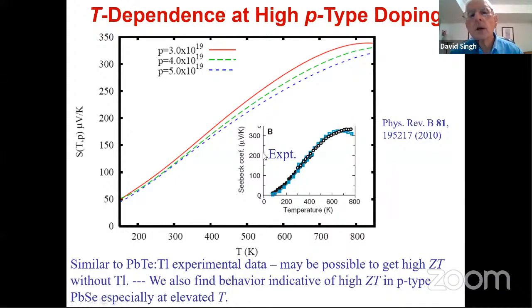And this is some experimental data. And the experimental data agrees very well with the theoretical curve, which you might think is sort of uninteresting. But it is interesting. And the reason it's interesting, this was work from 2010 that I published then. The reason it was interesting is this was not the standard experimental data for lead telluride. This was experimental data for what was called a very special kind of lead telluride, which had thallium in it, which was thought to change the band structure. But the calculation was not for that, and thallium is poisonous, as you might know.